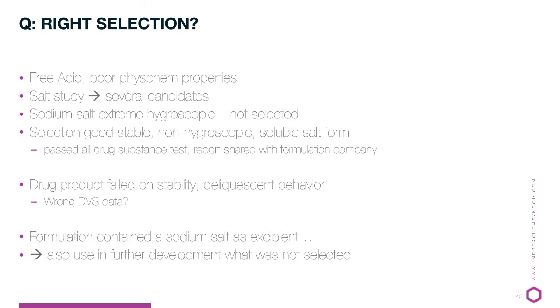Second in line, a good stable, non-hygroscopic and good soluble salt form was selected, and actually it gives good results in all tests. The report was shared with the formulation company. That company started to work with this material. And in the end, we had a drug product that failed the stability because it was extremely hygroscopic.